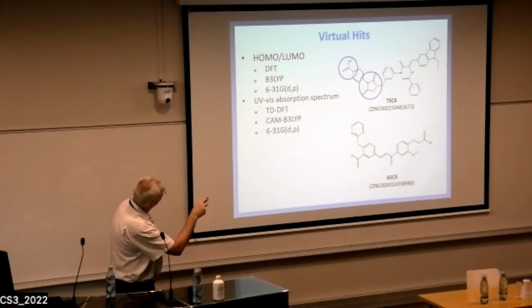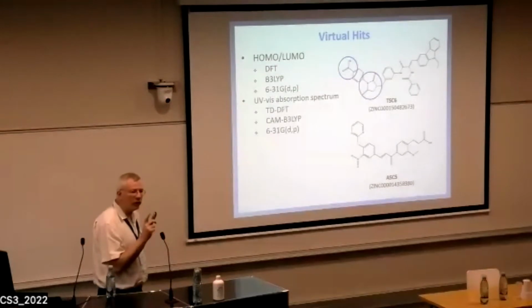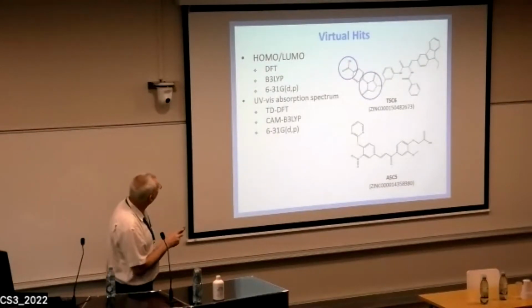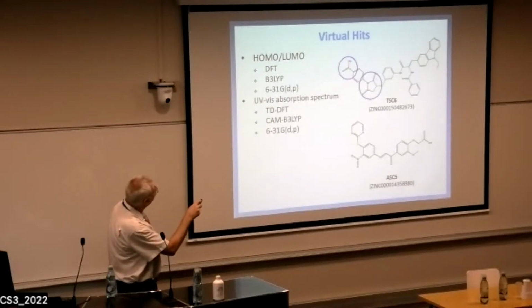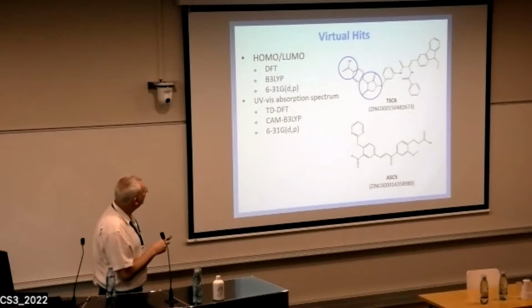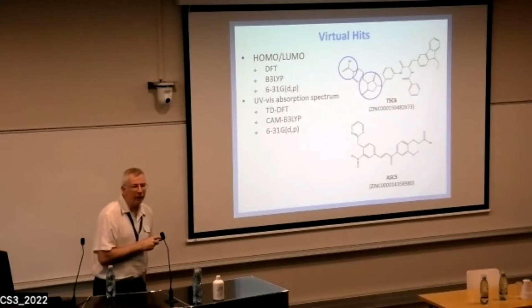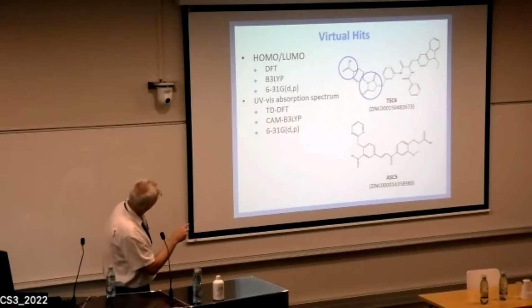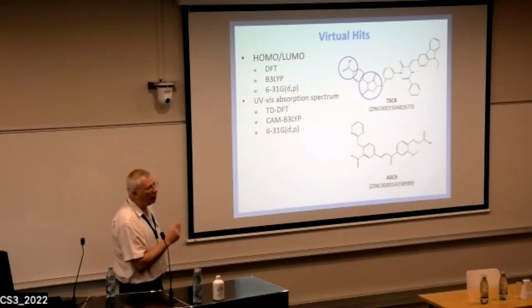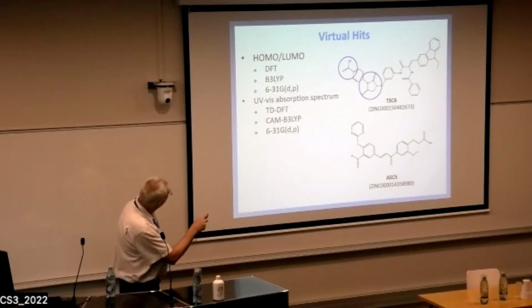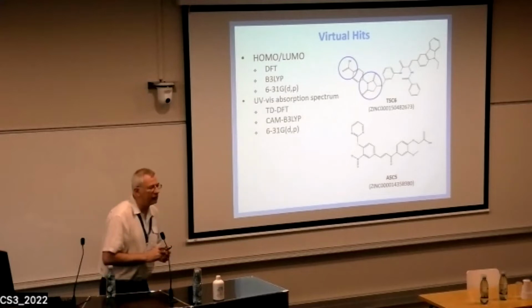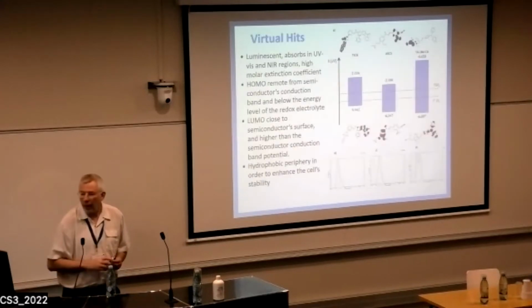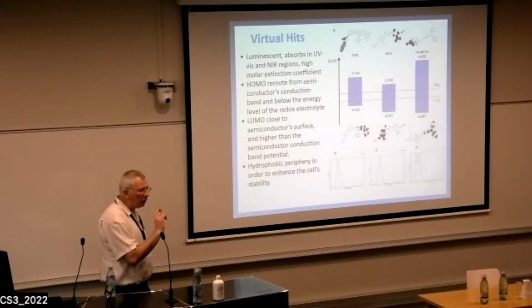We wanted to calculate the HOMO and LUMO energies because their energies are important for the dyes. We used DFT with this functional and this basis set. And then we also calculated time-dependent DFT in order to calculate the absorption spectrum. Again, it is important. So we used this functional and this basis set. And these are the results we got. So why did we do it?